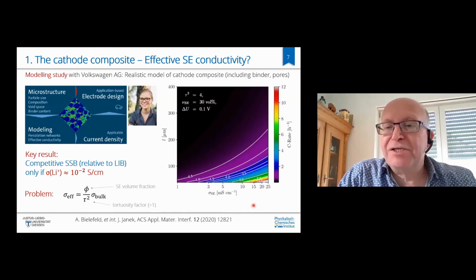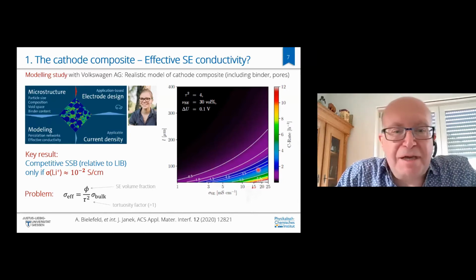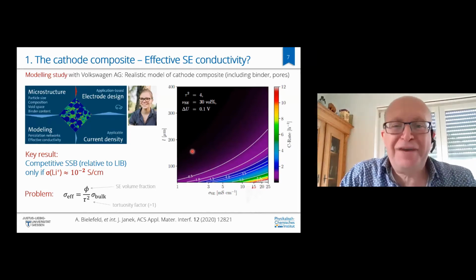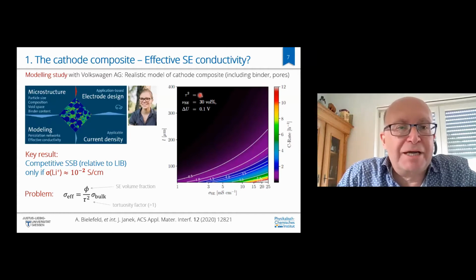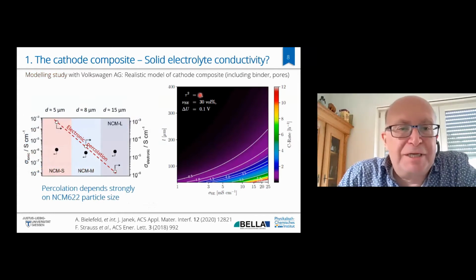And if we like to see a certain C rate, let's say 1 or 2 C, then the color here is the C rate. The solid electrolyte conductivity that is needed to achieve that has to be already in the order of 10 millisiemens per centimeter and better. So the 10 millisiemens per centimeter are a necessity simply to get enough ionic percolation, enough effective ionic conductivity in the cathode composite, and she translated that of course into the tortuosity. Here she assumed a tortuosity factor of 4, and I think this is something which we already demonstrated, that the percolation paths in a solid electrolyte are really critical.